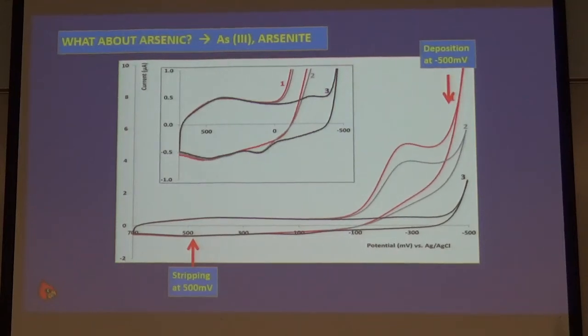Now, when I say arsenic, I'm talking about arsenic 3. There are lots of forms of arsenic. Arsenic 3 is probably the worst one. It's certainly the easiest one to work with electrochemically. So here, arsenic 3 is being reduced to arsenic metal, plating out on the electrode. Here, that arsenic is being stripped off. So we apply our deposition step by stepping out to about minus 500 millivolts. We strip it by stepping back to about plus 300. But it's the same deal as copper, more or less.